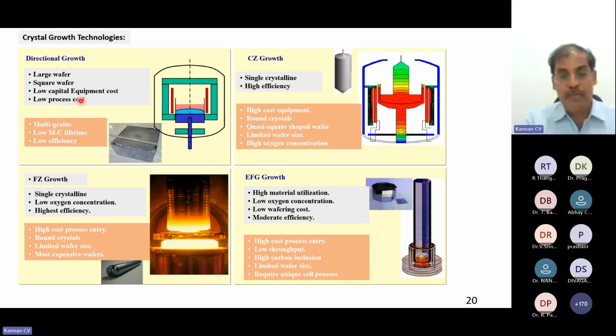That's the reason maybe a few years before, industry was focusing more on the multi-crystalline growth, because with the low cost you can produce high numbers of wafers. But the disadvantages, because it is multi-crystalline, with multiple grains, overall minority carrier lifetime is low. That means when the sunlight falls on it, electron hole pairs will be generated, and the lifetime of those minority carriers is relatively lesser here, because you have multiple grain boundaries. So they will be trapped in the boundaries, so that minority carrier lifetime will be very small, so that you may not get the desired efficiency. And that's the reason conversion efficiency is very low.